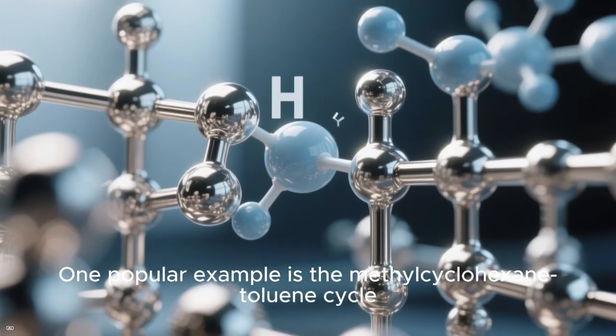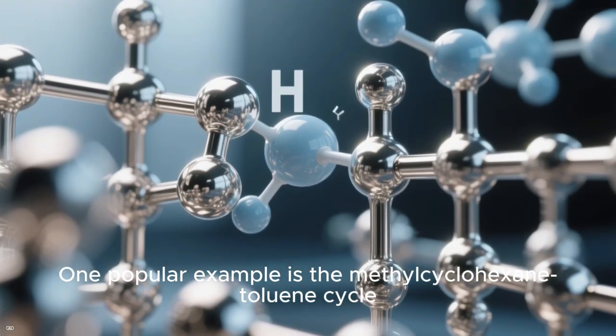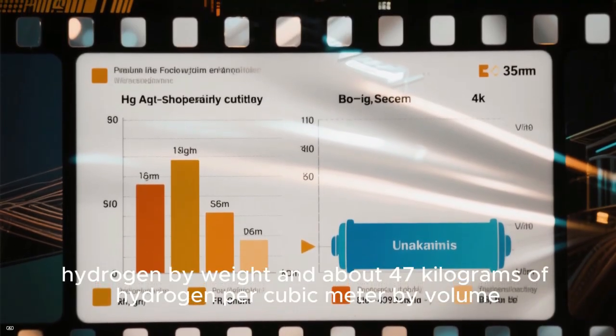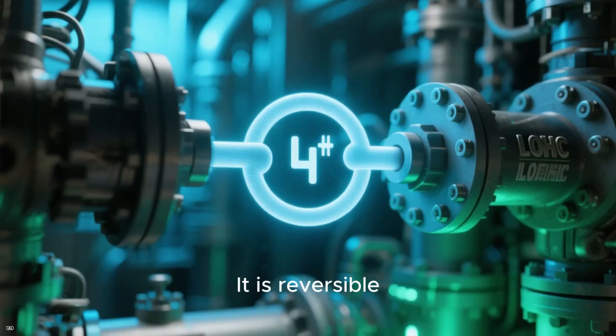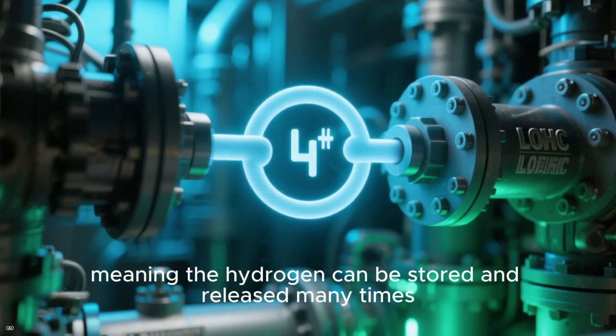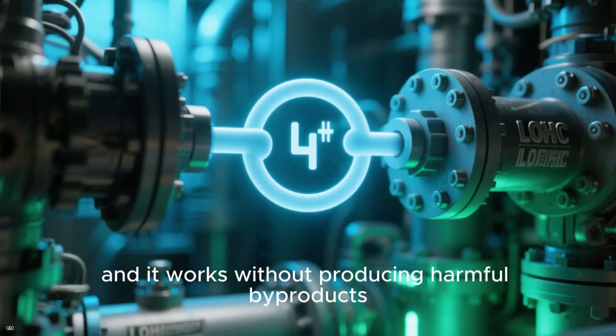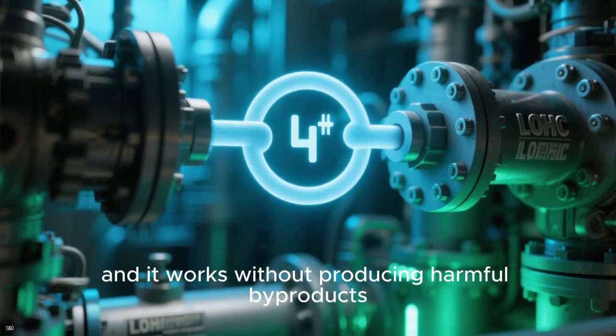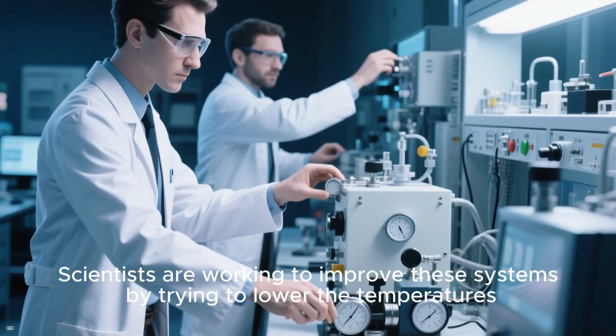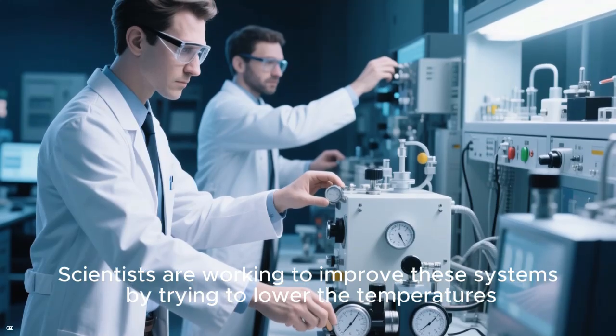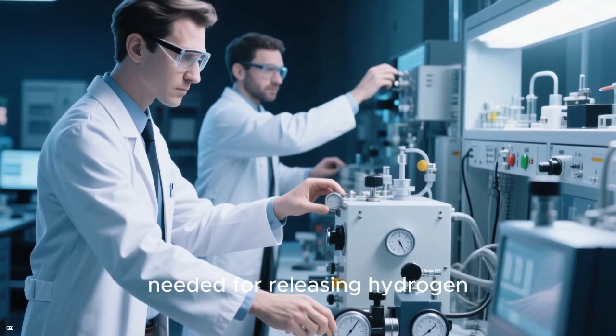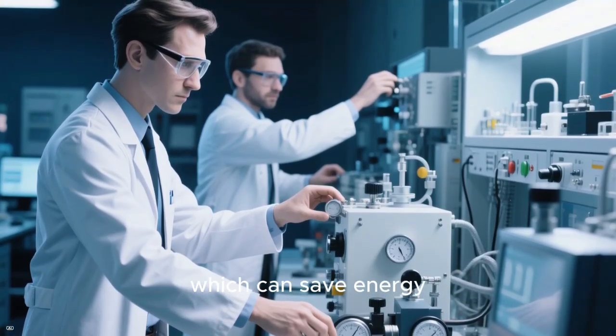One popular example is the methylcyclohexane-toluene cycle. This system can store 6.1% hydrogen by weight and about 47 kilograms of hydrogen per cubic meter by volume. It is reversible, meaning the hydrogen can be stored and released many times, and it works without producing harmful byproducts. Scientists are working to improve these systems by trying to lower the temperatures needed for releasing hydrogen, which can save energy.